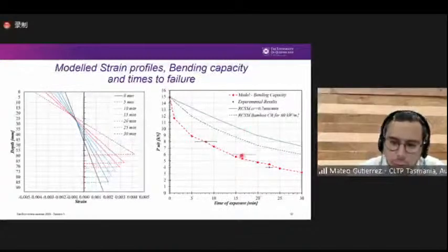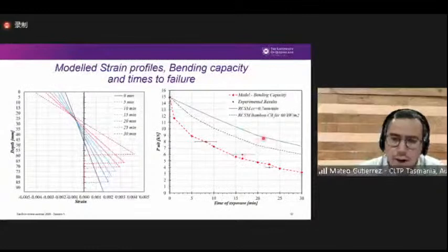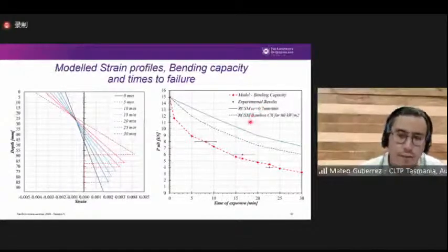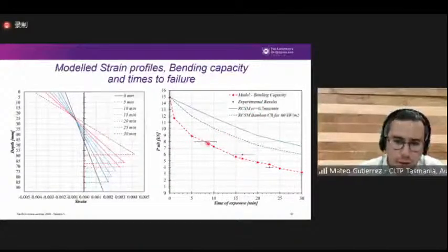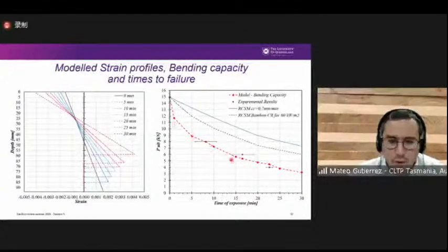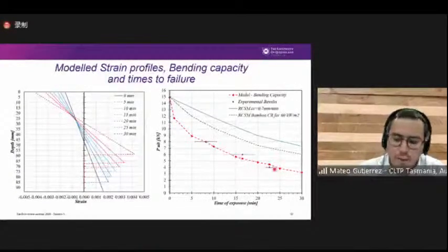Here the red dots show the experimental results. So you can see that the experimental results are actually quite far away, and this reduced cross-section method using standard charring rates and charring rates obtained from bamboo tests over-predicts the capacity of the bamboo beams. However, the dashed line is the model that we created, and you can see that the model actually matches pretty well with the experimental results, and it's able to predict the performance of the beam.